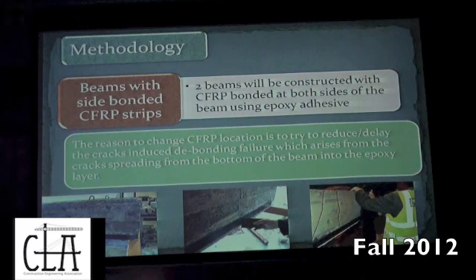First we talked about the control, then we're going to have the 2 beams that are attached with what the industry considers the traditional approach, which is attaching them from the bottom. As we said, we believe the failure is going to be caused by the cracks instead of reaching the limits of the laminates themselves. So we decided to try different alternatives to how to attach them in order to try and increase the strength of the beam. So we decided for the second 2 beams, we're going to attach the laminates from the side, as you can see here. We thought this might delay the crack moving from the beam into the layer of the epoxy itself to try and reach the limits of the CFRP itself.